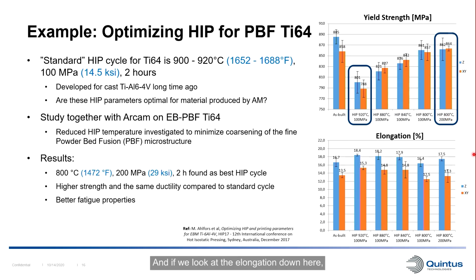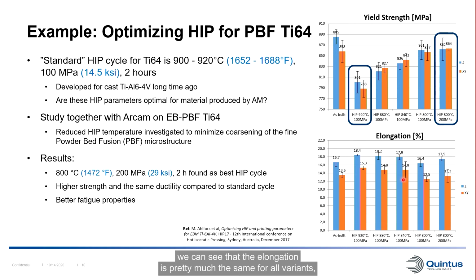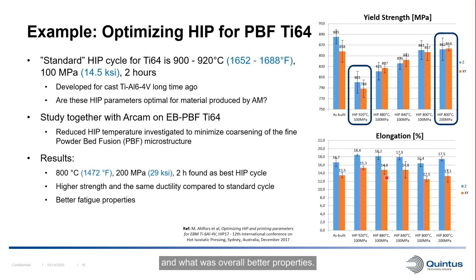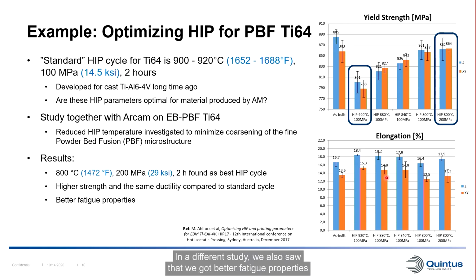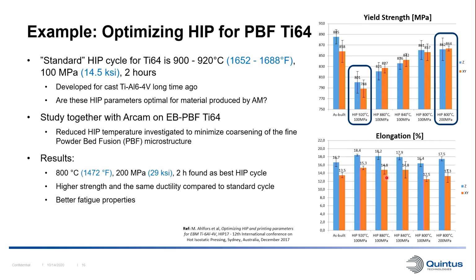And if we look at the elongation down here, we can see that the elongation is pretty much the same for all variants. So just by tweaking the HIP parameters a bit, reducing the temperature and increasing the pressure, we could get higher strength at the same ductility level, and overall better properties. In a different study, we also saw that we got better fatigue properties with this HIP cycle compared to the standard cycle.